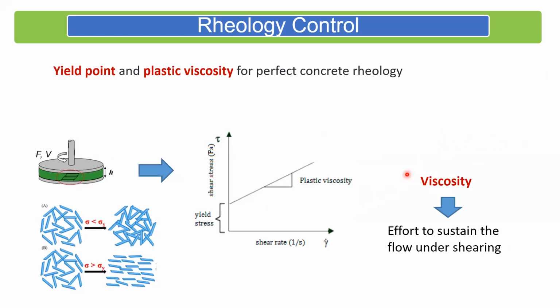Now, there's also another thing we need to understand, and that is, once I have initiated flow, suppose I shear the material, what is the effort required to sustain it? And that is viscosity. Suppose I apply a constant or increasing shear rate onto cement paste. Initially, I'll have to overcome the initial resistance that is shown here. The y-axis is shear stress. The initial resistance is the yield stress. With increasing shear rate, I will basically get an increasing resistance. And this is what we call the classical viscous response from any viscous liquid.